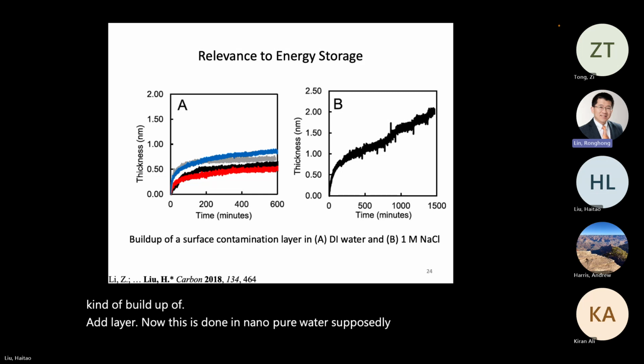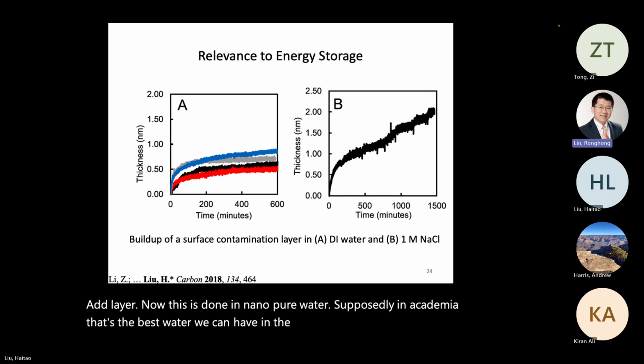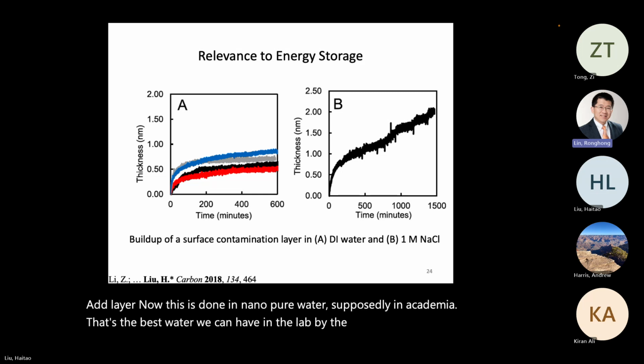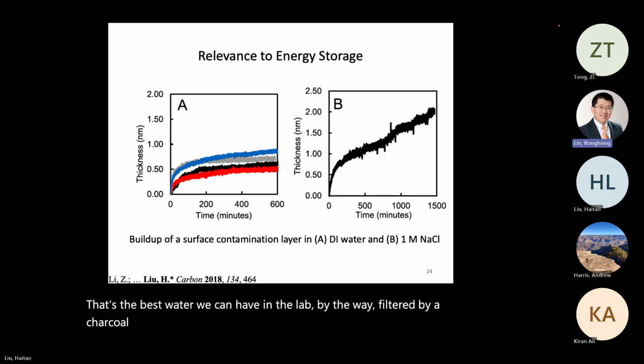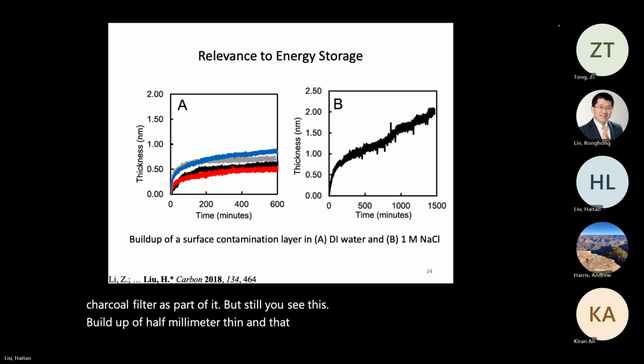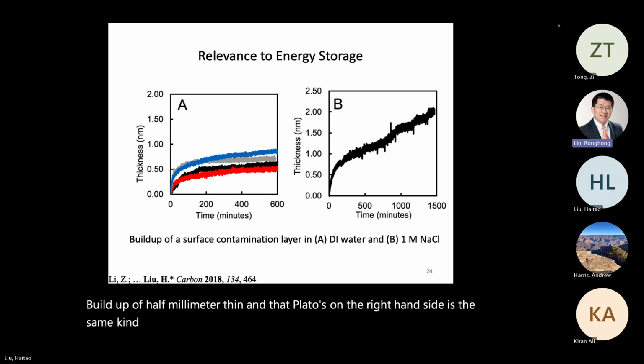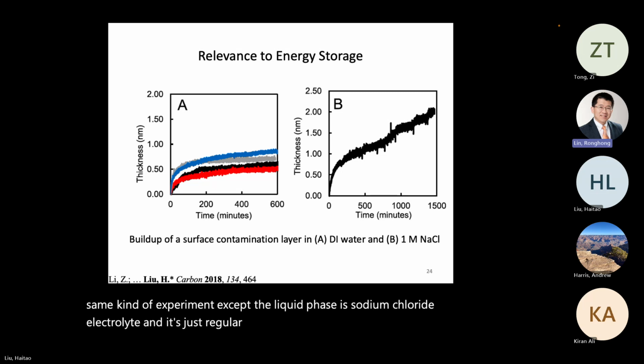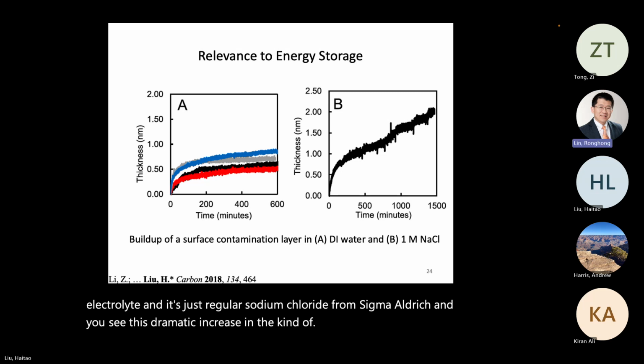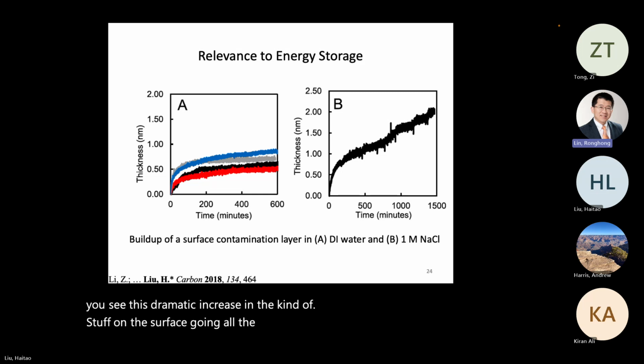Supposedly in academia, that's the best water we can have in the lab. By the way, filtered by a charcoal filter as part of it. But still, you see this buildup of half a nanometer thin, and that plateaus. On the right-hand side, it's the same kind of experiment, except the liquid phase is sodium chloride electrolyte, just regular sodium chloride from Sigma Aldrich, and you see this dramatic increase in the amount of stuff on the surface, going all the way to about 2 nanometers.